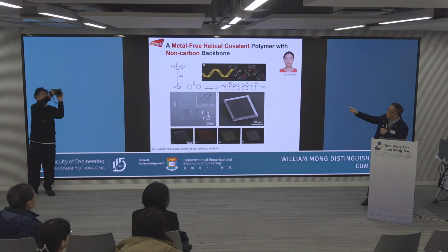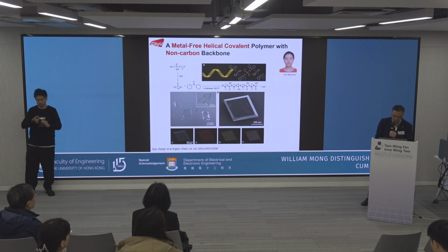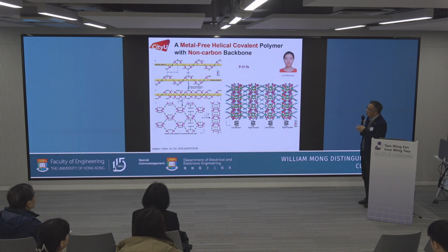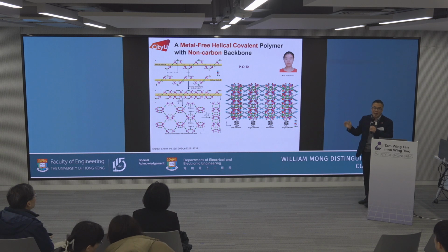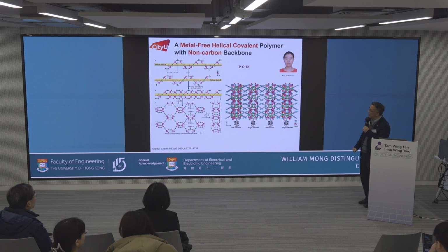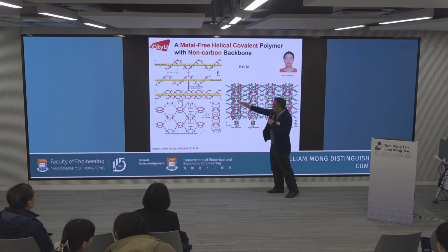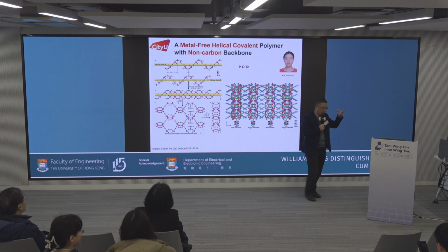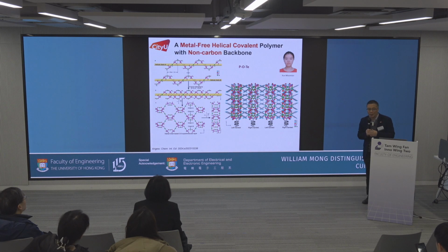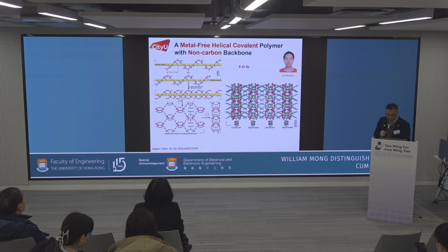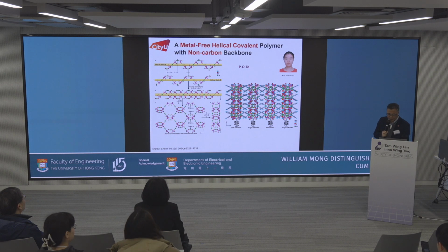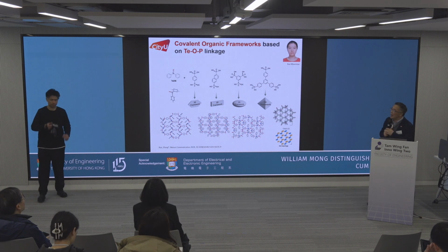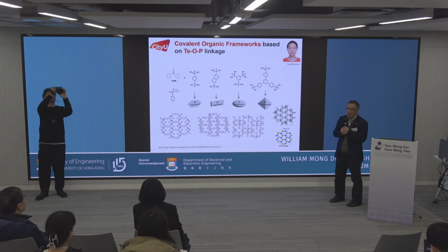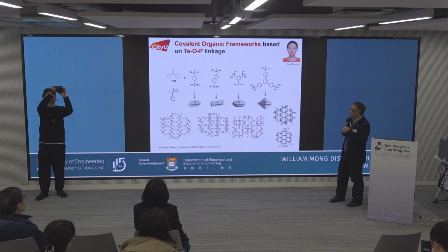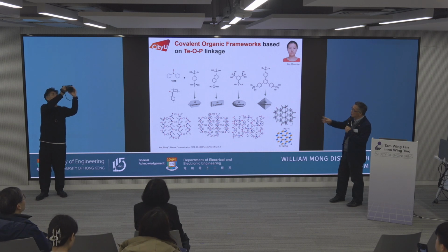We have the tellurium oxygen phosphate. Okay, and since this chain is a helix, in the crystal we have the right-hand chain and also the left-hand chain. And you can see one layer is right hand and another layer is left hand. And then the whole crystal in space is actually symmetric. Okay. So following this idea, it's possible for us to use organic phosphate to replace the inorganic phosphoric acid. Now it looks like it works very well.